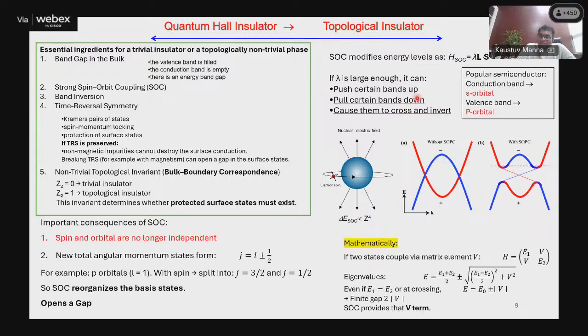So in this material, when you have band inversion, let's say the popular semiconducting material, the conduction band is, not always, I should not say always, in most of the popular compounds, made with S orbital, whereas the valence band is made with P orbital. Now you have the hybridization of that. Under spin orbit coupling, spin and orbital are no longer independent of each other. So we have to invoke J. J means L plus S to L minus S. The moment you form L plus S and L minus S, the Hamiltonian is 2 by 2, and if you solve it, the energy you get is E naught plus minus V. What is the V term? The V term is the consequence of this LS term. That means the net energy after incorporating the SOC gives energy plus V, energy minus V.